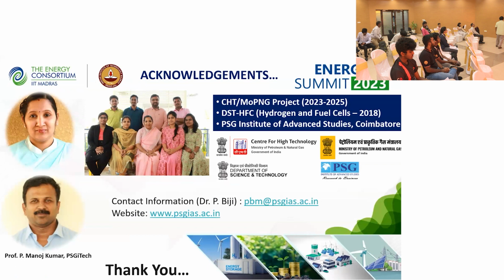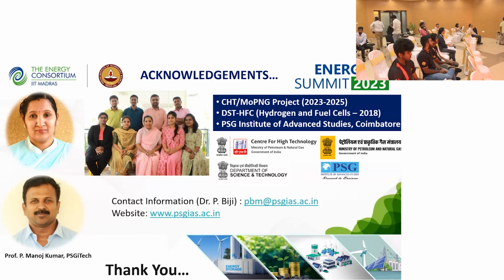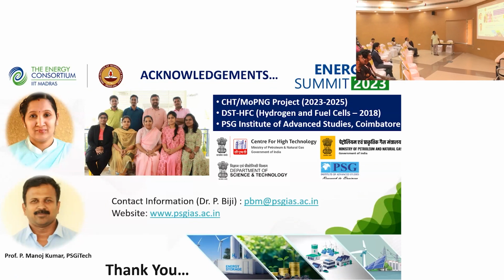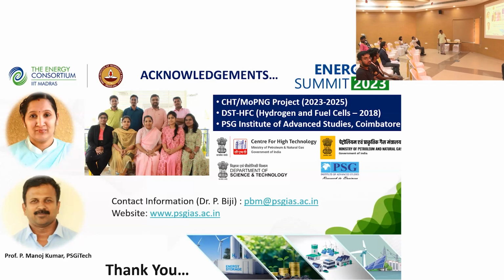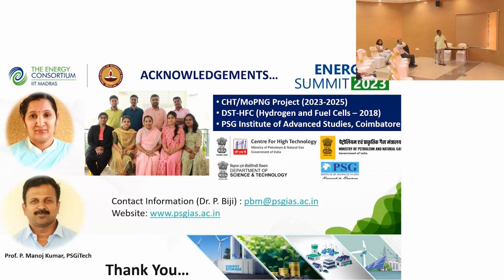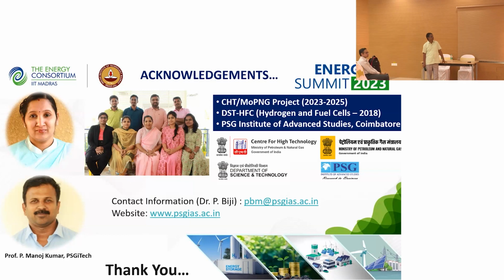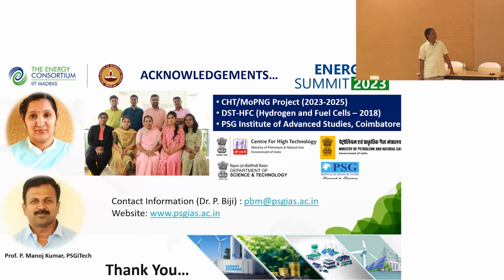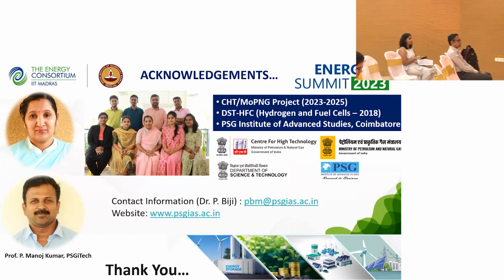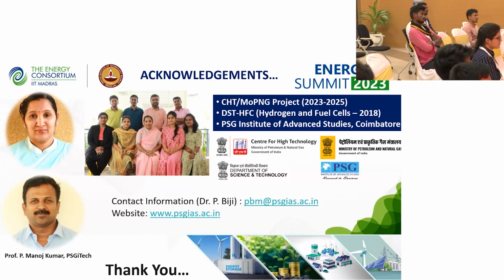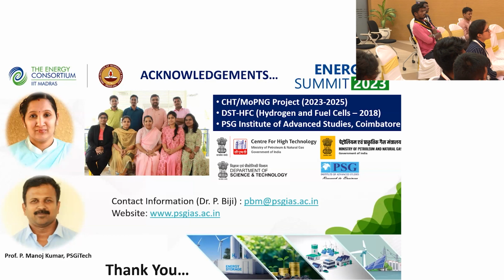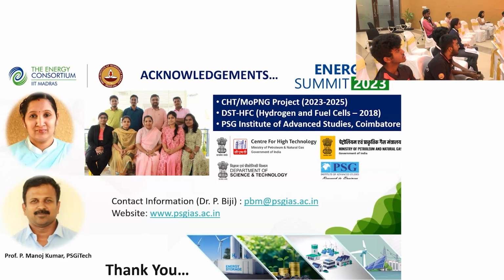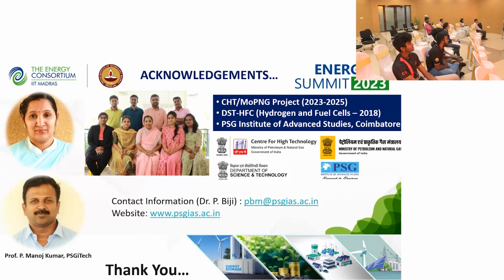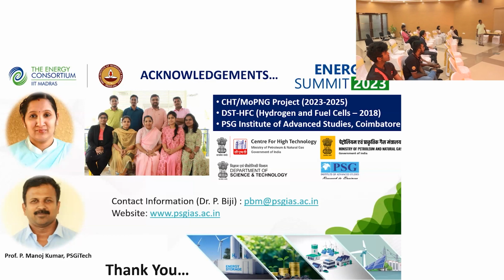Initially, PSG Institute of Advanced Studies was investing in this fuel cell research in our institute to create basic infrastructure like electrochemical workstation and all. Further, we received a grant from DST HFC. With that, we tried to develop durable mesoporous carbon nanofibers. Our idea was a little bit different. After creating these mesoporous carbon nanofibers, we tried to deposit anti-corrosive layers like titanium nitride on the surface of the mesoporous carbon nanofibers, which could effectively improve the durability of the layers.